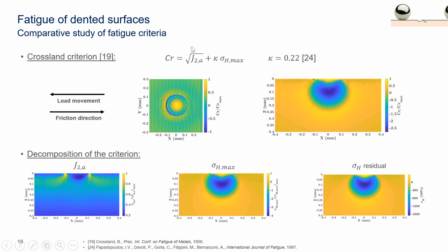Now, if you check the effect of each parameter, the first one is only the shear stress, through the von Mises criterion, von Mises stress. You can see some peak of stress at the surface and nearby the dent. This is the effect of hydrostatic or mean stress, and this is the sum, in fact. When you sum both, you can compare to your experimental results.